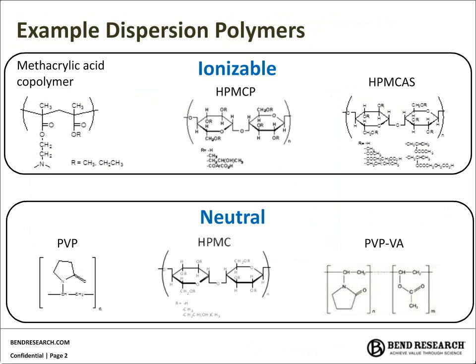And here we've listed some example dispersion polymers, and we usually break the world up into ionizable polymers and neutral polymers. In the case of ionizable polymers, such as HPMCAS, these polymers have special properties in that when they're in the neutral state, they're effectively fairly hydrophobic. Therefore, they don't pick up a lot of water, and that leads to enhanced physical stability. However, when they wet in a physiologically relevant media, the succinate groups deprotonate, and what you end up with is an amphiphilic charged polymer molecule that can then have surface activity and effectively stabilize high energy forms of drug in colloids. From the neutral perspective, these are also very useful materials, and oftentimes we'll use neutral polymers when a drug has acid sensitivity or requires gastric dissolution for its specific absorption profile.